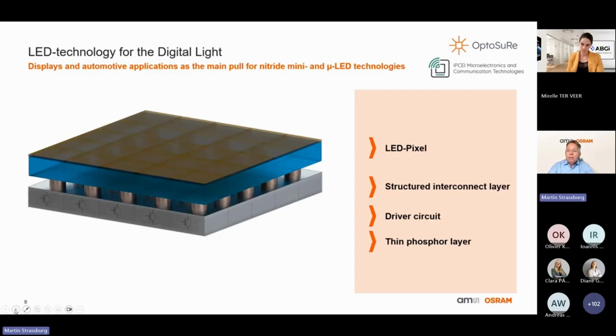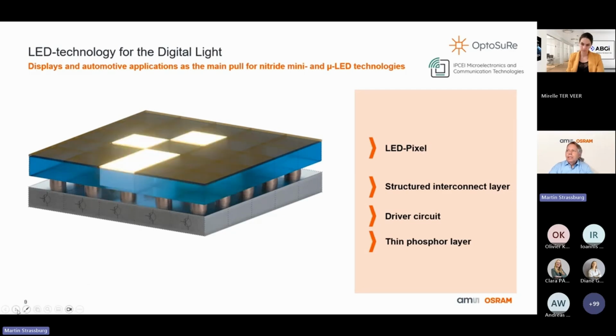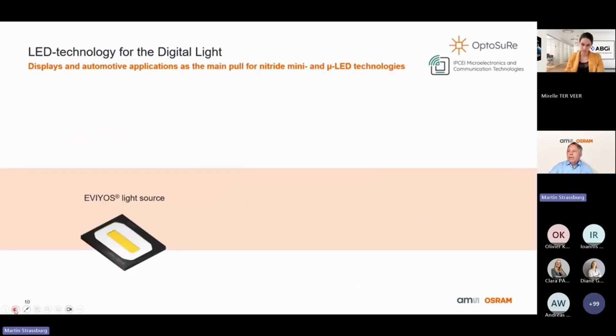steps, and that is the deposition of a converter material, a phosphor material, which converts the blue light into white light. We therefore use thin phosphor layers of nanograin phosphor to reduce the losses and to increase the absorption, so that we can really have a very thin layer that does not impact too much the aspect ratio of each pixel. And when you then operate such a pixel, you can have individually steered, addressed pixels of the LED and have micro LEDs, as shown in a certain pattern here, and you can use them for several applications.